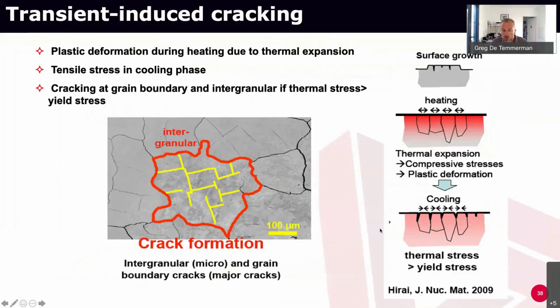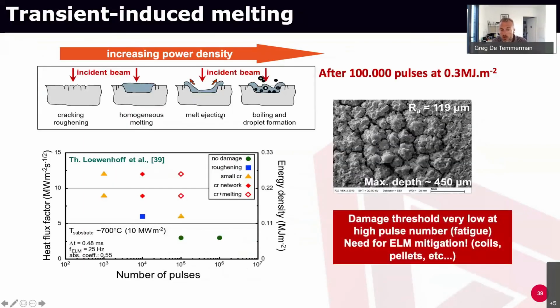And what happens, and I won't go into the details, is you have a lot of cracking because you have a continuous cooling and heating, and basically you form cracks, whether they are intergranular or transgranular. And if you go higher in power, then basically you could melt the surface. You can melt like 100 or 200 microns of the material every time, and then you do that continuously. And because you are in a plasma with strong magnetic fields and strong currents, while you have a liquid pool of material which is liquefied, solidified, it basically forms large shapes. You can see an example of a surface after only 100,000 pulses. And you see that we had a roughness of about 0.1 millimeter already, with a lot of melted islands on the material.